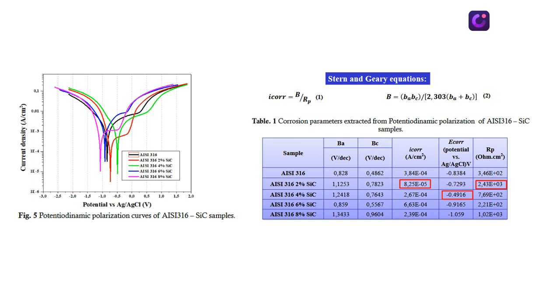As for the corrosion currents, the sample with 2% reinforcement shows the lowest current density, indicating that this material is efficient against corrosion due to the potential present and allows less current to pass through the system, reducing the capacity of the material to trigger corrosion processes, presenting greater resistance to polarization.